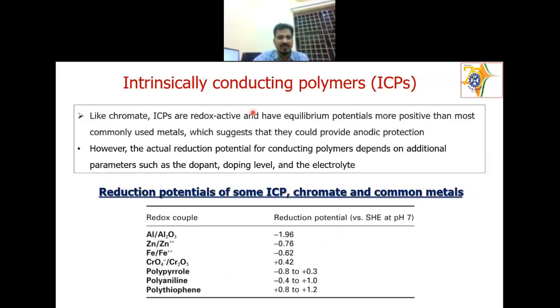Why are we using ICP? You can see that, like the chromates, the ICPs have equilibrium potential more positive than most commonly used metals. If we use aluminum, zinc, and iron, these are the most commonly used metals, or alloys based on these metals, for industrial applications. So you see the reduction potential is minus 1.96 for the aluminum couple, minus 0.76 for the zinc Zn2+ couple, and minus 0.62 for iron. The chromate is positive, and all the ICPs are also positive. It's very positive with respect to the metal ions. It varies depending upon the dopant or doping level and the electrolyte or the surrounding in which it is being used. So doping, I will come to that.